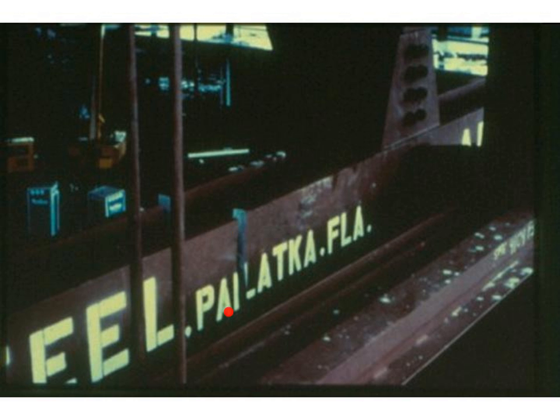And you can see the fracture of the flanges where this truss, the bottom cord was in the H orientation, if you will. Now, the second shot shows this in a little more detail, and the detail here is helpful to identify the contributing factors. Now, the first thing I'd like you to notice is that the weld itself did not fracture. This cracking is occurring in the base metal. Now, admittedly, it's a cracking that's welding related, but we need to make sure that we start by understanding that it was the base metal that was fracturing.